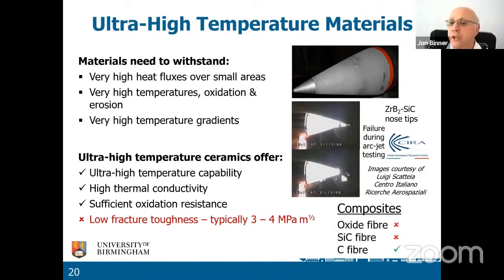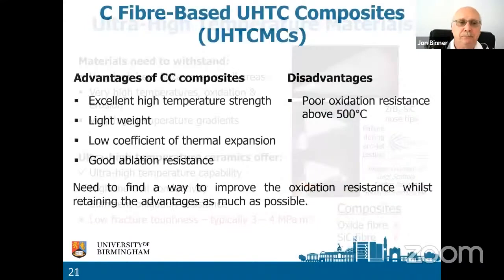So the solution is to use composites. We can't use oxide fibers. They won't survive more than about 1,000 or 1,200. We can't really use silicon carbide fibers. They won't withstand more than 1,400 or 1,500. We can use carbon fibers, but they oxidize readily, so we've got to protect them from oxidation.